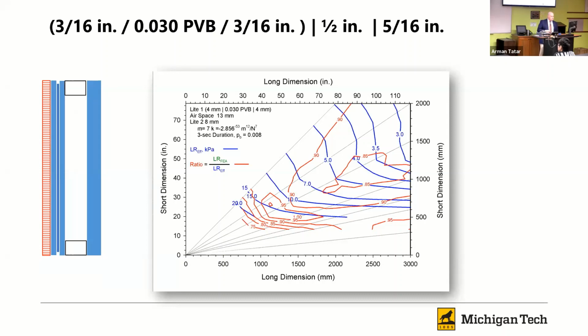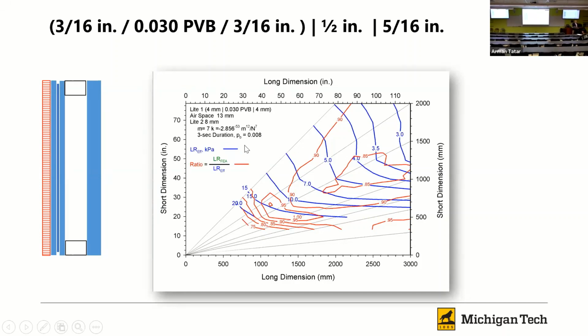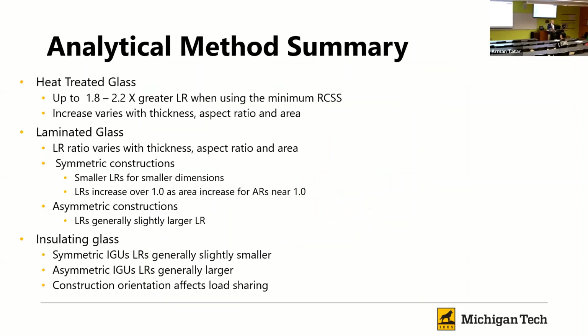All right, in this one, I've actually done a little bit different analysis. I wanted to compare if I use the effective thickness method versus using a full layered FEA model, to see how well the effective thickness model worked compared to doing a full FEA model. And we see that depending on where we're at, there can be upwards of 10 to 15% difference, at least in this construction. In different constructions, it can be more so for that process. All right.